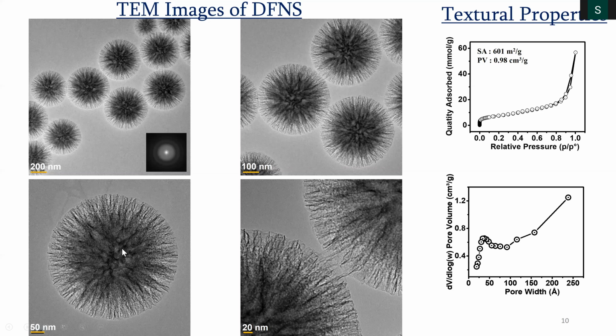And it looks like there is a solid core in here, but there is no solid core. It's more dense fibers at the center. That's why the electron transmission is weak, and that's why they are darker, this contrast difference. You see a pore surface area is around 600 in this case with a very good pore volume. And the uniqueness is the pore size distribution.